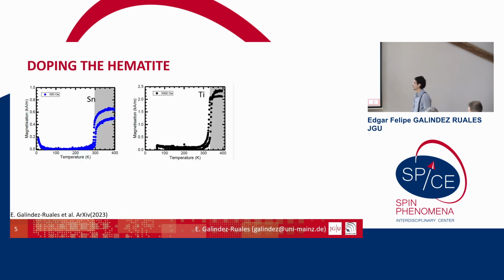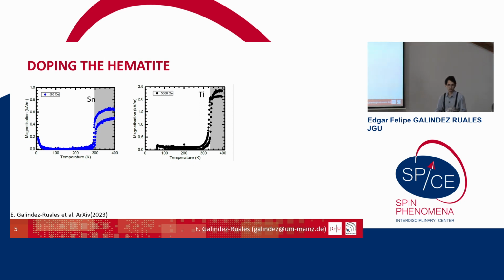So we dope the hematite, and when you dope the hematite, there are some changes in the material per se. The first change is that hematite is well known to have a Morin transition. At low temperatures the spins are pointed up, and then at 260 Kelvin they are in the basal plane, right? And they are a little bit canted.